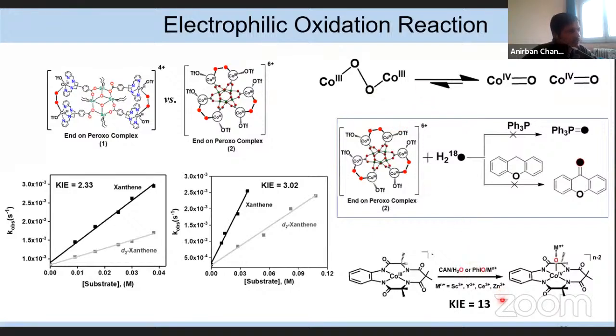Also, another thing is that if we look into the literature, we can see that for the metal oxo species, the KIE values are relatively very high. This is the example from Professor Nam's group, where they reported cobalt 4 oxo in presence of scandium, and there they observed the KIE value of around 13, but here you can see the KIE value is relatively smaller. So this low KIE value and also the 18O water experiment confirm that there is no high valent metal oxo species involved in the electrophilic oxidation reaction, and it is only the endon dinuclear cobalt peroxo which is showing this electrophilic reactivity.